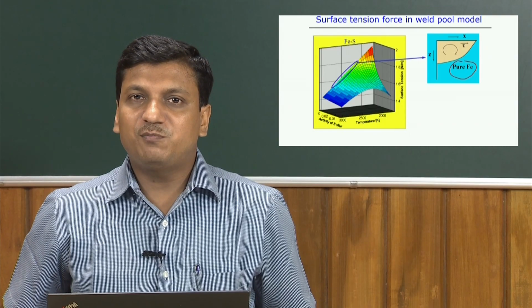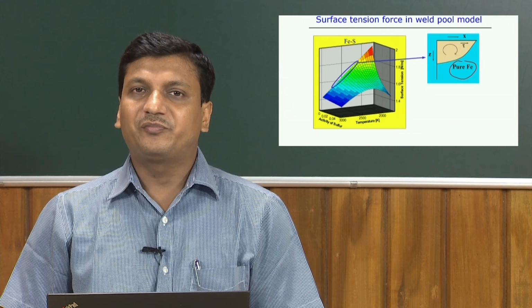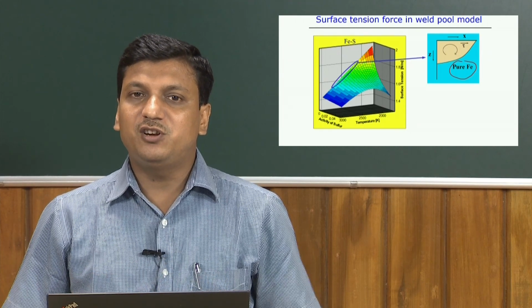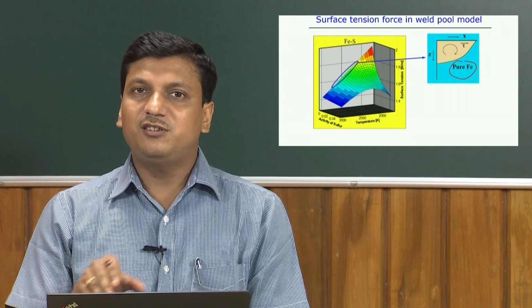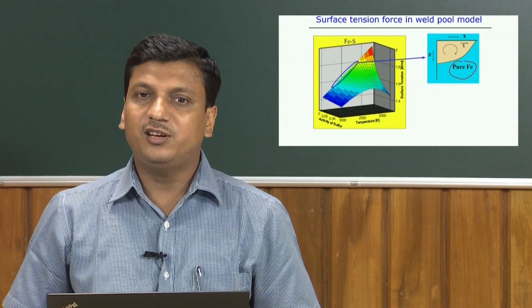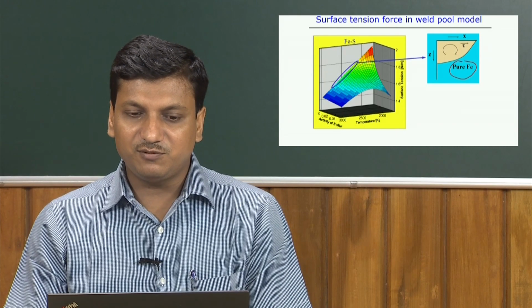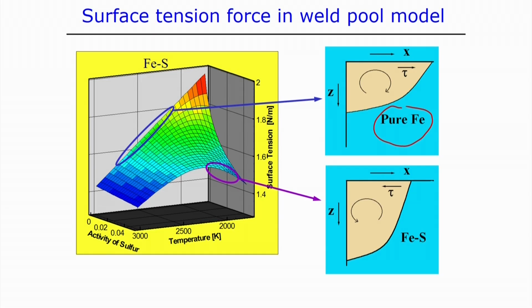So, that means in case of pure iron, without any effect of the surface active elements, normally we can expect a wider width and low depth of penetration, depending on the nature of the material flow, or the nature of the Marangoni convection that happens within the weld pool. But in other cases, if we look at this other part, in this case the metal has a considerable amount of surface active elements. It is a binary Fe-S system, and the metal has a considerable amount of surface active elements at a certain temperature. So, in this case the shear stress is the viscosity times the velocity gradient.